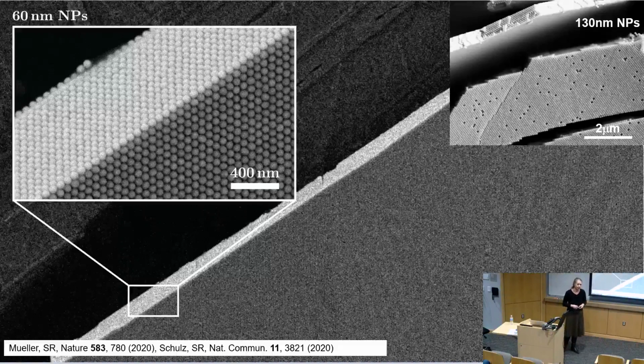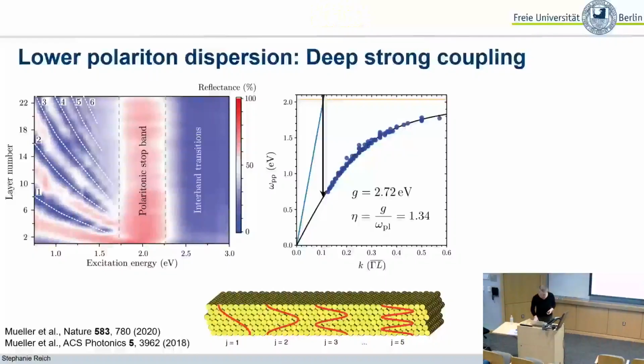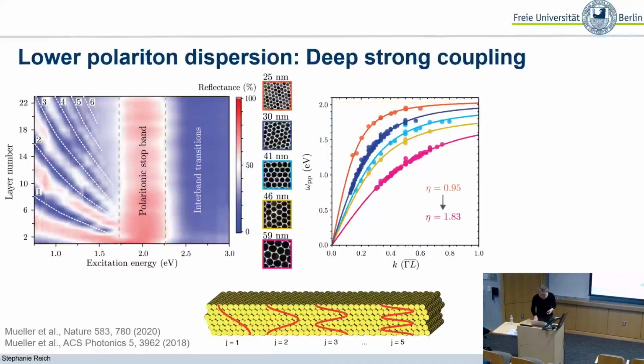How does that affect your coupling effect, this light matter coupling? So the light matter coupling depends essentially on the packing density. Whether you change the size of the gold nanoparticles or whether you change the distance doesn't really matter. The defining quantity is how much metal do you have inside a volume and how much vacuum or polymer do you have inside a volume.